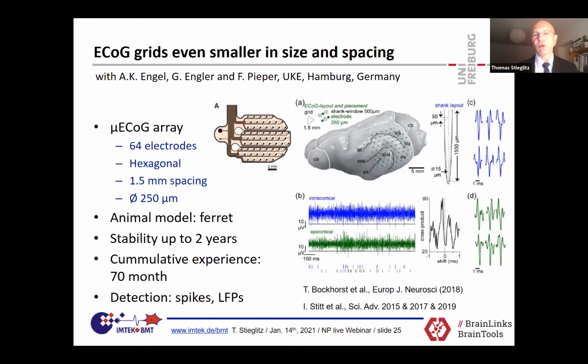Ferret has a smaller brain than a macaque monkey. That means the curvature of the brain gets larger. And even there, those arrays with a thickness of 10 microns, and here electrodes with a diameter of 250 micrometers, worked well. And the exciting thing for me was that due to the good conformability and adherence of the array to the surface of the brain, my colleagues were able to record spike-like activity over those arrays, not only local field potentials.